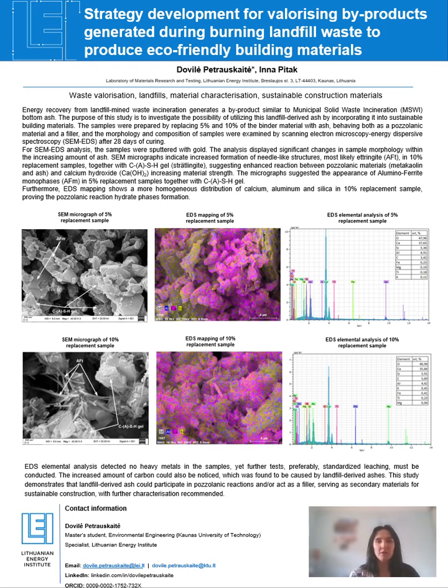And importantly, no heavy metals were detected in either sample, which is pretty encouraging for environmental safety. And a slightly higher carbon content was observed, likely originating from organic residues in landfill-derived ash. So carbon in these ashes could appear as inorganic aluminosilicate structures combined with organics or carbon-based molecules. It could also be carbonates or even elemental carbon particles.